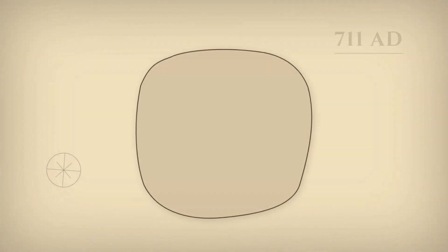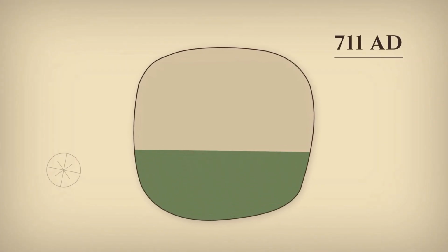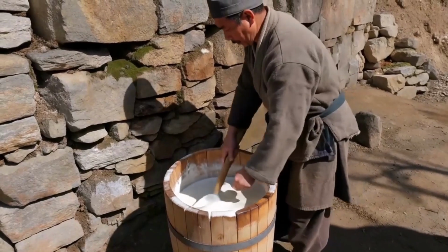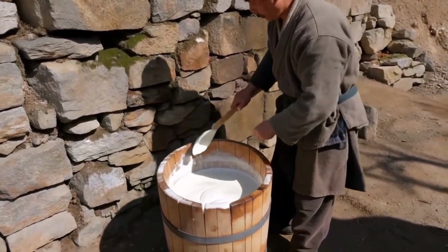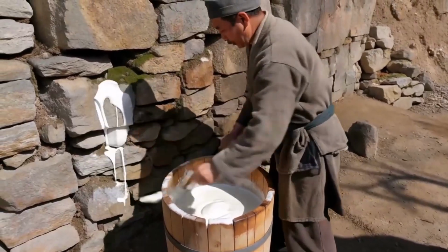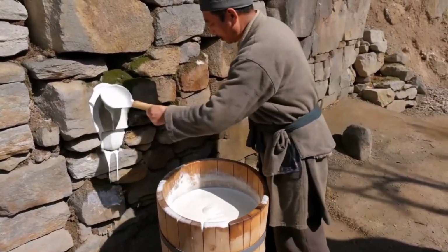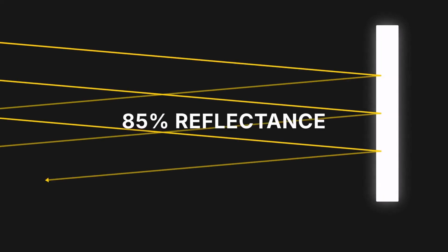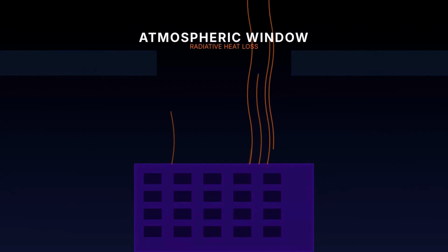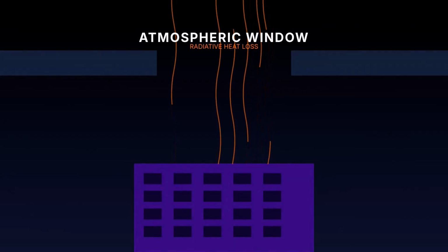Beginning with the Moorish settlement of the Iberian Peninsula in 711 AD, architects across what is now Andalusia applied cal, hydrated lime dissolved in water, to exterior walls as standard construction practice. The resulting white finish achieved solar reflectance above 85%, while simultaneously maintaining the high infrared emittance required for radiative heat loss into the atmospheric window.